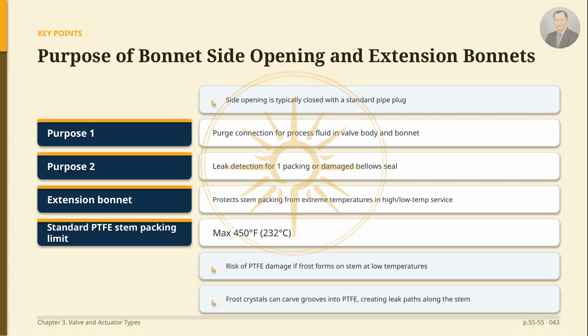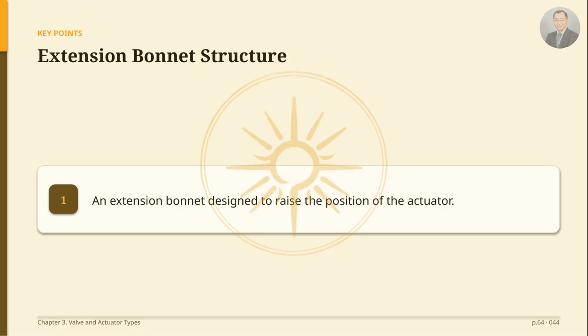Next, extension bonnets are used in high or low temperature service to protect the valve stem packing from extreme process temperatures. Standard PTFE valve stem packing is effective for most applications up to 450 degrees Fahrenheit, 232 degrees Celsius. However, it is susceptible to damage in low-temperature processes if frost forms on the valve stem. This is because frost crystals can cut grooves into the PTFE, creating leakage paths for process fluid along the stem. This is an extension bonnet designed to raise the position of the actuator.